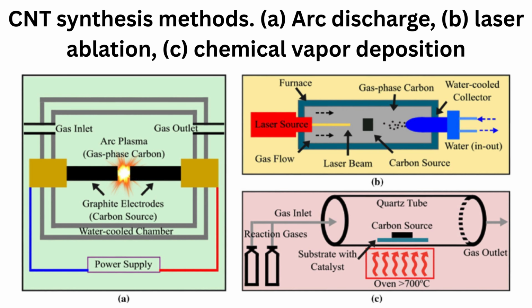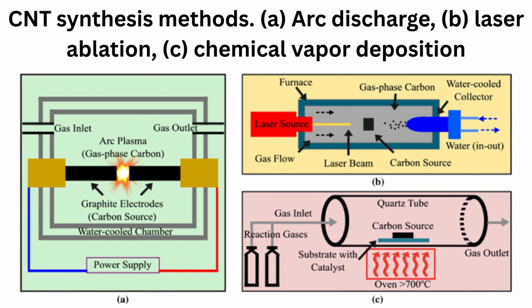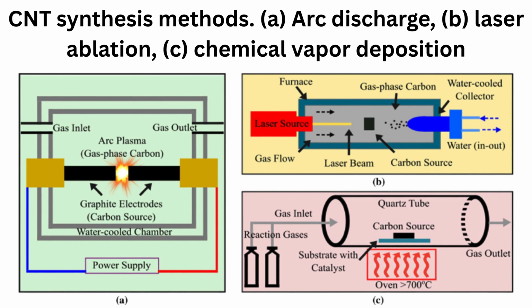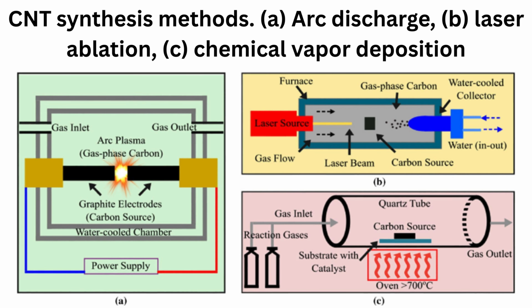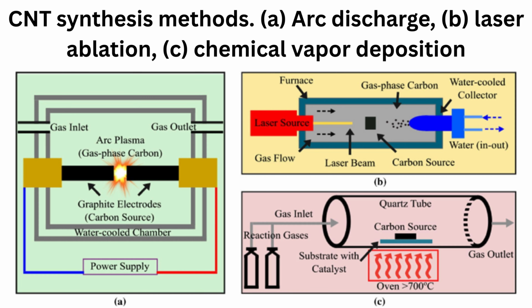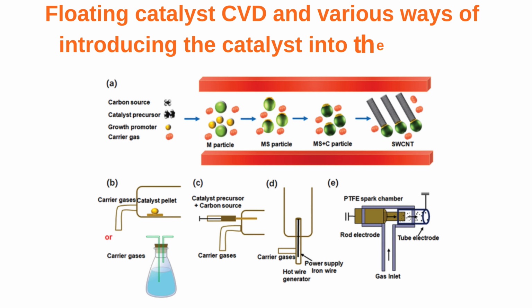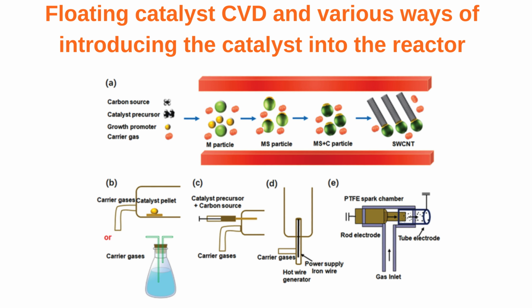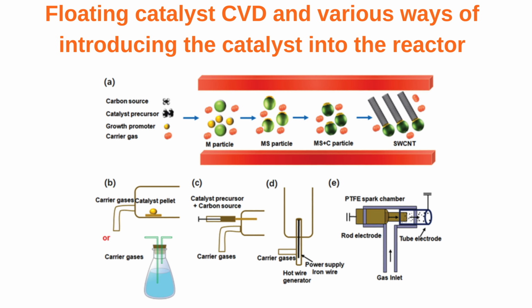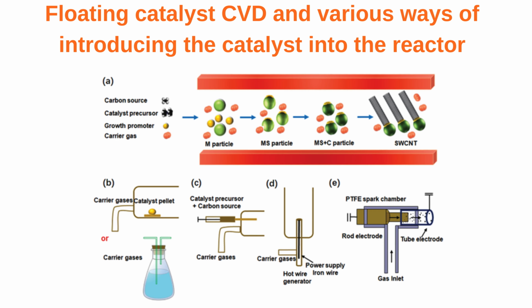However, the most common method for the synthesis of CNTs over the last 2 decades is based on CVD, wherein passage of a carbon-containing precursor gas over a substrate in a reactor allows for reaction between the precursor and the surface, leading to gradual buildup of CNTs. The substrate can incorporate a catalyst, commonly nanoparticles made of iron, nickel, cobalt, or combinations of these metals, which can nucleate CNT growth and allow it to proceed at a lower temperature.